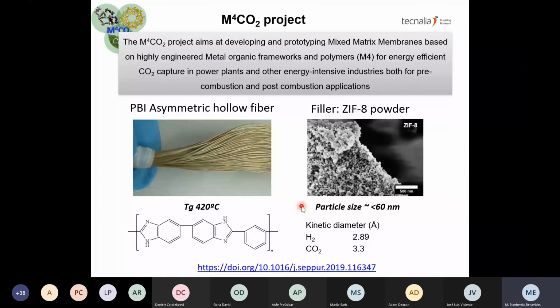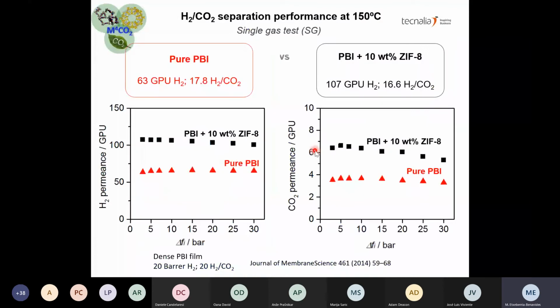PBI has shown to exhibit the highest selectivity among polymer families. However, the low permeability is among the main drawbacks of PBI membranes. So in order to improve the permeability of the PBI membranes, ZIF-8 MOF particles were introduced in the polymer matrix. With the introduction of the ZIF-8 particles, we are aiming to improve the permeability of the membrane. So during this project, both pure PBI and mixed matrix membranes were prepared.